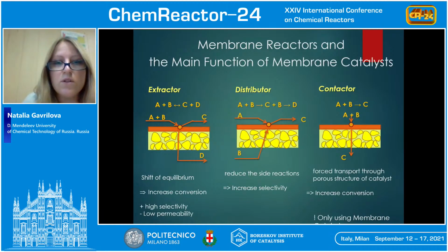According to their function, membrane catalyst reactors are divided into extractor, distributor, and contactor. The majority of studies in this area are devoted to one of the possible modes, the reactor extractor. The idea is to selectively remove one of the reaction products from the reaction volume. This allows influencing the equilibrium of a chemical reaction and shifting it toward the formation of products. This leads to an increase in the degree of conversion. This type of membrane reactor is recommended for high temperature reactions involving hydrogen. There are two other types of membrane reactor, distributor and contactor, but these modes are less studied.